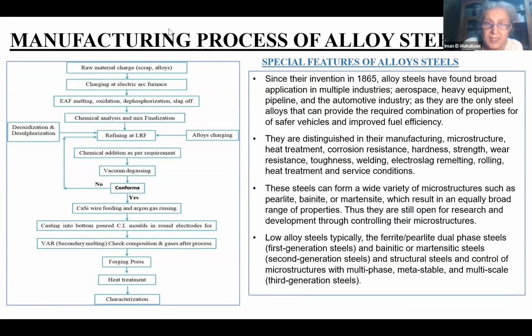Some steps are common, like the charging, using the electric arc furnace, chemical analysis, and the refining in the ladle furnace. But then you have to charge the alloying elements, and you have to make calculations for the right alloying elements. And in many occasions, you need a vacuum degassing step, because you have to eliminate all the sources for entrapment or for tramp elements presence. You have to get rid of the oxygen and the hydrogen and other things that may get into the steel. You may need wire feeding, argon gas rinsing, and other processes before you pour your product and take it to either the continuous caster or to the forging process or whatever.